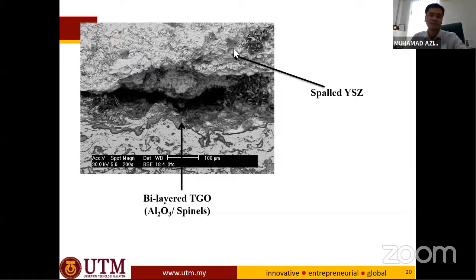If the oxygen goes through, this is the ceramic coating just now, this is your bond coat, and this is the TGO. But because you have a large amount of oxygen diffusion here, you create a lot of spinels, nickel oxide, chromium oxide on top of the TGO. So this becomes compressive stress to the layers. In the application of a gas turbine engine, for example, it's not stationary, is it? It is vibrating, and then temperature changes, which we call thermal shock. Any change of this compressive condition will lead to the spallation of this ceramic coating. So this is the problem which we need to control.